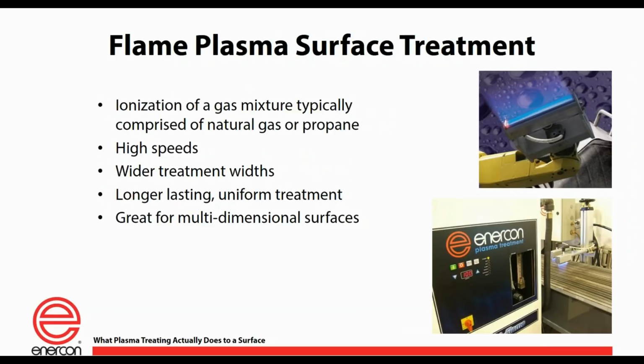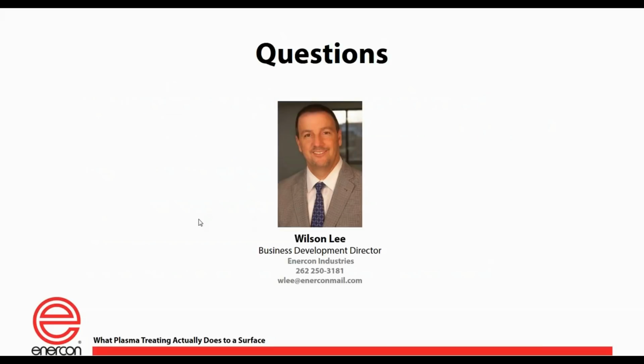And we also have flames. And this is going back to when I got confused a little bit earlier and got tongue-tied. I apologize again. These are adding carboxyl groups to the surface instead of the hydroxyl groups. Many times on many surfaces, they'll act exactly the same. Going back to that dash application, you can use blown ion plasma on a dashboard and it works just fine. Flame in this case is just a little more forgiving. We can throw the flame a little bit further so we don't have to be quite as precise on the distance to the part. And we can make a flame head virtually as big as you'd like. So if we're trying to cover large, wider distances in a shorter cycle time, flame tends to be the best way to go.